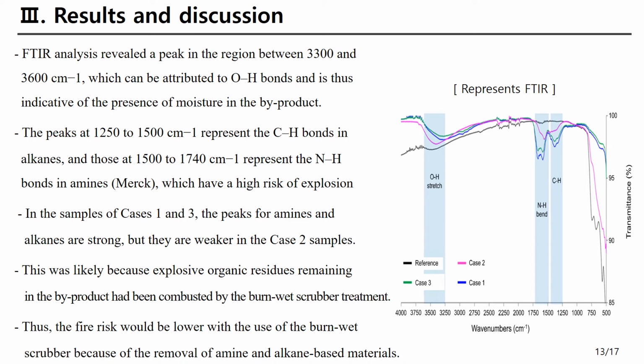FTIR analysis revealed a peak in the region between 3,300 and 3,600 per centimeter, which can be attributed to oxygen and hydrogen bonds, and is thus indicative of the presence of moisture in the byproduct. The peak between 1,250 and 1,500 per centimeter represents the carbon and hydrogen bonds in alkanes, and those at 1,500 to 1,740 per centimeter represent the nitrogen and hydrogen bonds in amines, which have a high risk of explosion.